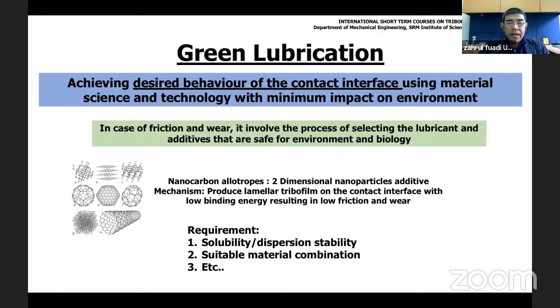And this has at least two requirements. You will need a fluid which has good solubility or dispersion stability for the graphene or the 2D material. Well, it will disperse in mineral oil, but if you want to use an environmentally and biologically safe solution, maybe you can use bio oil or vegetable oil.